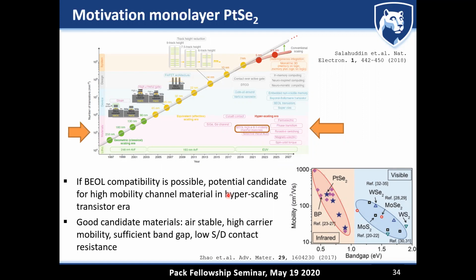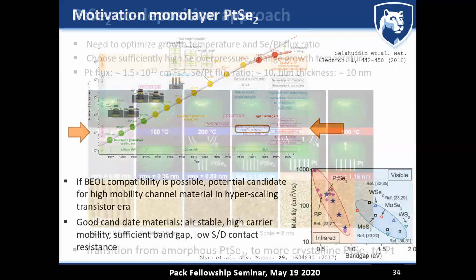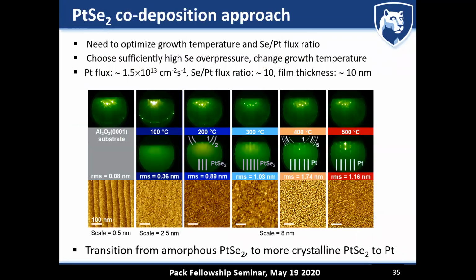So good candidate materials for back end of line integration of semiconducting materials have to be layers that are air stable, that have a high carrier mobility, sufficient band gap, and then ultimately, if you want to build a transistor out of this, a low source drain contact resistance. And platinum diselenide magically meets all of these requirements. Now, if you're trying to grow platinum diselenide, it turns out to be really hard.